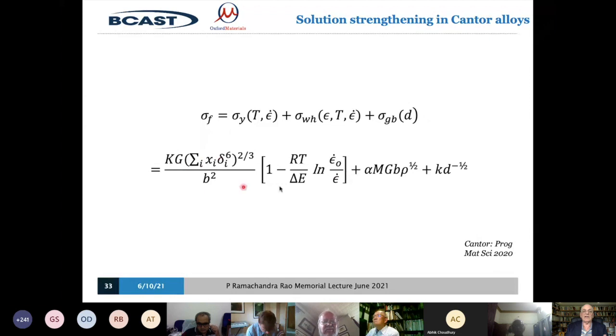As the dislocations move around, they get in each other's way, so you get what's called work hardening, classic Taylor work hardening. And if there are different crystals, as you saw, there is more than one crystal, then the grain boundaries, the crystal boundaries get in the way, and you get a classic Hall-Petch grain boundary effect. So the total strength of the material, these are well known. This is exactly what you get in any material, but this is the new one that's much stronger.